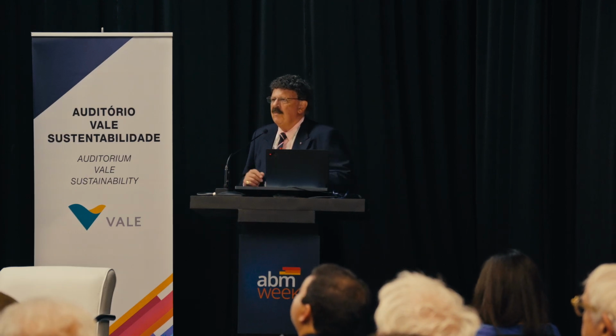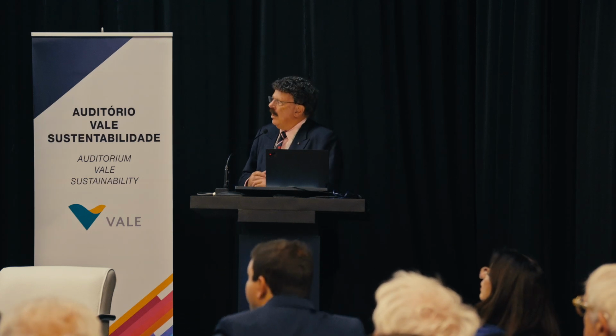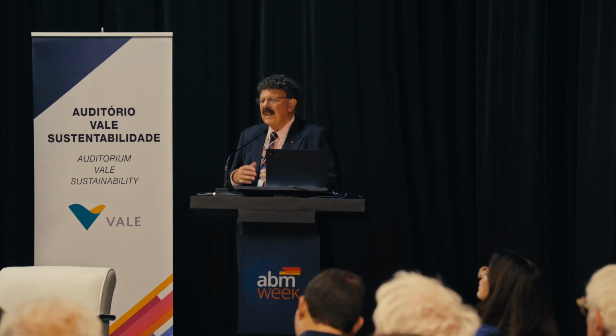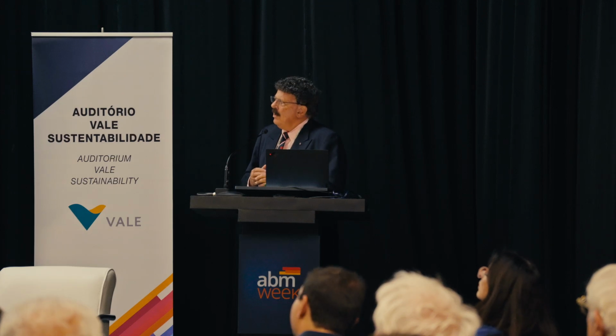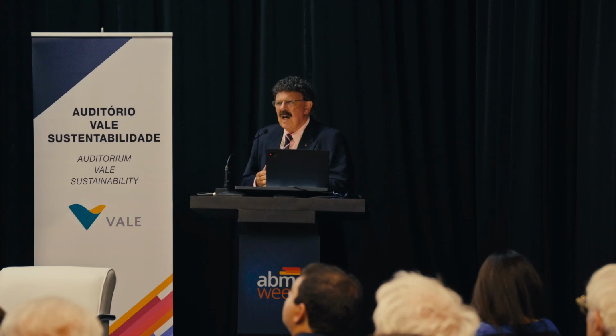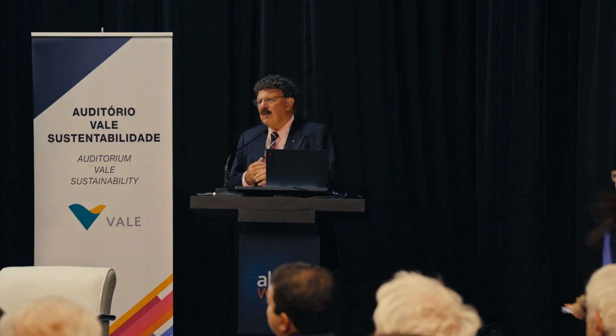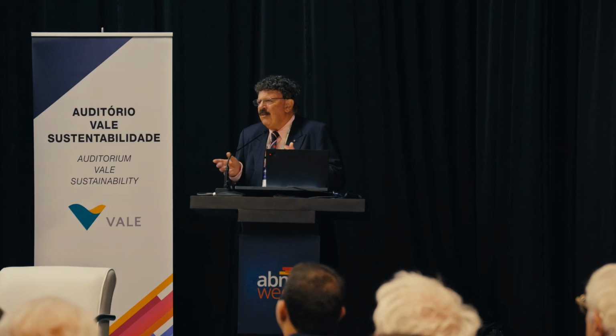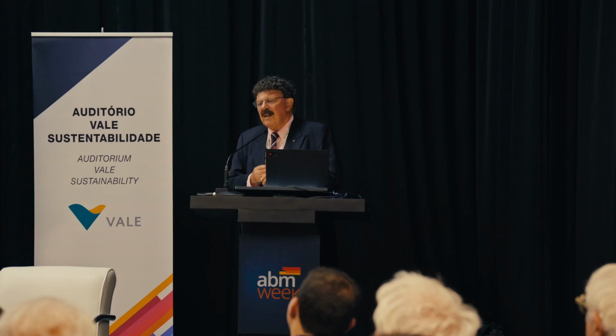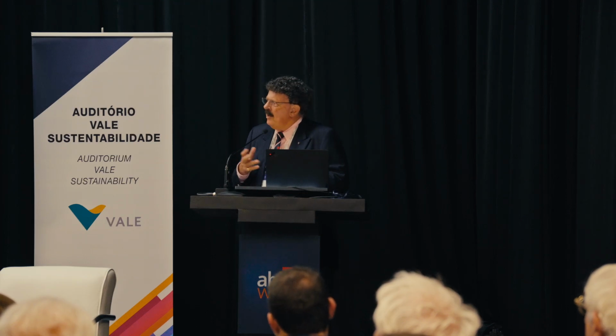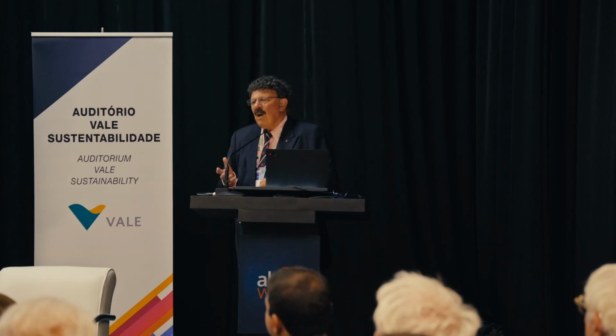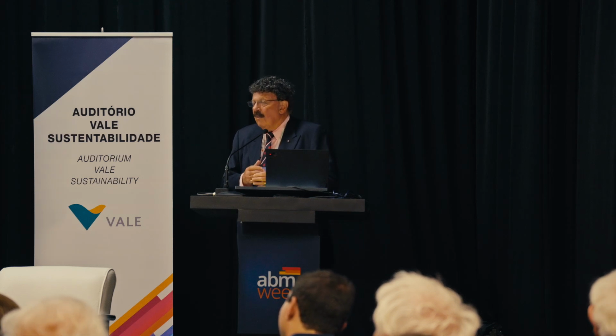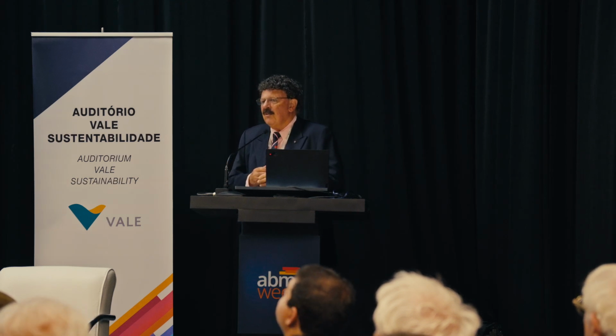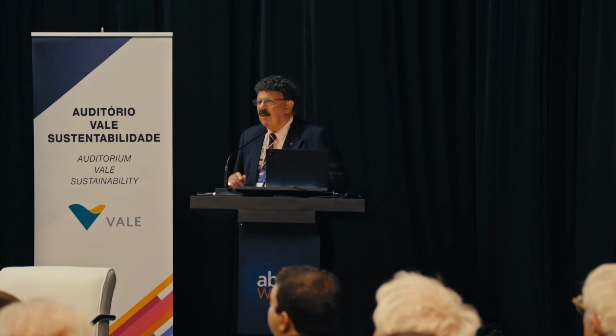So let's look at the FCC first. These were the ones that were first invented. They're sometimes called the Cantor alloys. They're chrome, cobalt, nickel. Sometimes they have manganese and iron in them. People never studied these multiple principal element alloys. Most of our alloys are single element with a number of other materials added. You know, steels, iron dominated. Superalloys are nickel dominated. But these have almost equiatomic, in many cases, applications of elements with very, very different crystal structures, but they end up with a single phase material, in many cases, not all, but these alloys did.